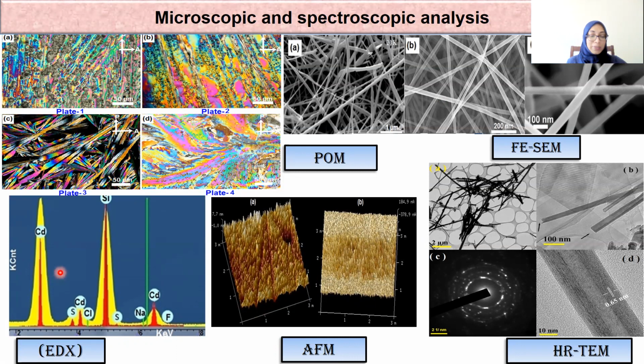Then energy dispersive X-ray spectroscopy, that is the EDS pattern. EDS spectra is shown here. The peaks of Cd and S in the EDS pattern indicate that the K shell element cadmium and the L shell element sulfur exist with an atomic ratio of 50.5 to 35.5. It also indicates that the CdS nanostructure dispersed liquid crystal is associated with other chemical elements like sodium, chlorine, fluorine.